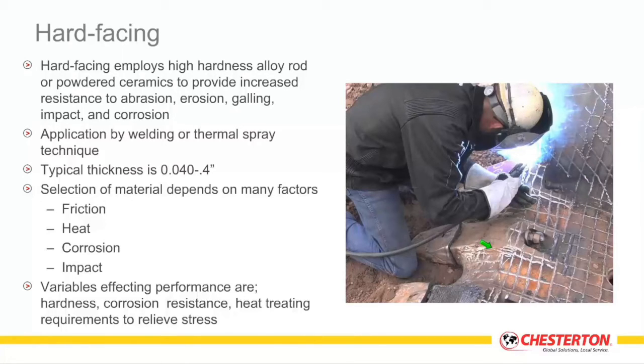The selection of the material that you would choose would be based on multiple factors, such as the friction of flow across the surface, the heat, the corrosion resistance and impact resistance. You can choose these high chrome carbide alloys, you can choose martensitic or austenitic rods, you can choose ceramics, tungsten carbides, chrome carbides. All these different materials will come into play. Variables affecting performance are going to be the hardness that you're looking for, the corrosion resistance that you're seeking, and the ability to absorb and withstand heat treating to relieve the stresses, because you are inducing stress into these base metals when you're welding the alloys. You want to make sure you're using compatible alloys if there's a corrosion mechanism in play. And you want to make sure that the alloy materials you're using have the suitable hardness to resist the wear factors that are going to be in play.